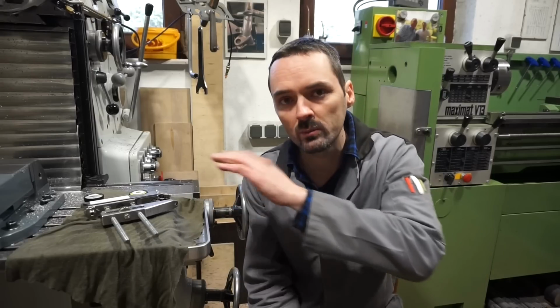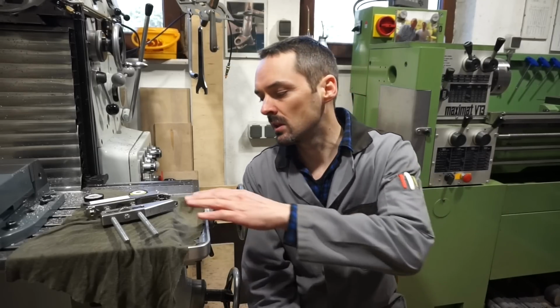With Rockwell cone and Rockwell ball method, which can also be done with this tester here, there is a non-linear relation, but that doesn't matter. With the aid of available tables, you can convert hardness to strength of a material. So strictly speaking, you can only make a qualified statement of material strength if you cut a tension test sample from the part. But in an approximative way, you can do it with hardness testing and convert the hardness reading